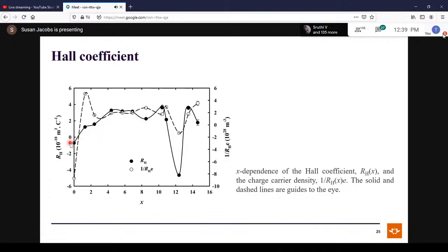We can see that for the 0 and the 12.4 atomic percent alloy, the Hall coefficient is negative. Whereas for all other alloys, it is positive, meaning the Fermi surface has predominantly hole-like morphology. So when there was no vanadium, it was negative. Now, upon adding vanadium, because vanadium is electron deficient, it compensated for the additional negative charge carriers, and therefore the RH became positive. Now, if you remember, this is also a signature for quantum criticality.